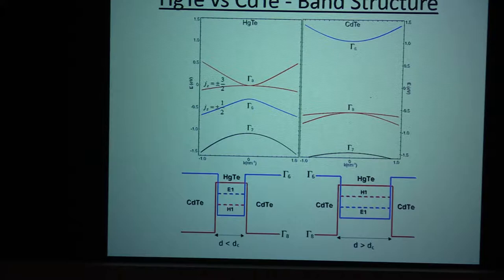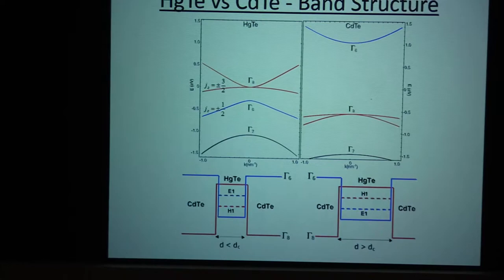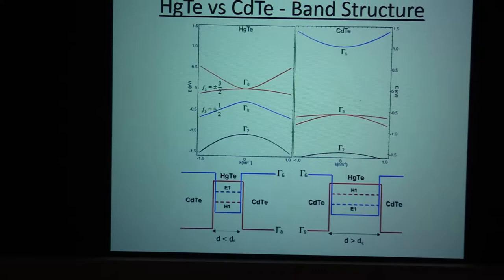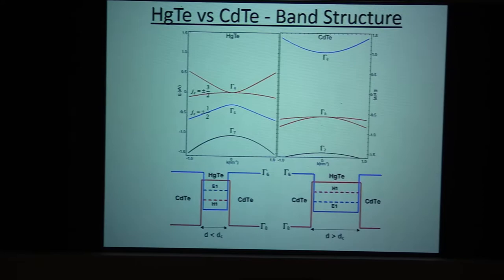So, if we want to actually make this into an insulator, the way to do it is to introduce some energy gap due to confinement. So, imagine we construct a quantum well, which is very, very narrow. So, now we sandwich, we grow a material that consists of mercury telluride, sandwiched between two barrier material cadmium telluride. In the cadmium telluride, you see that, indeed, the blue or the s-orbital sit above. This is the bottom of the conduction band, top of the valence band. And if the well is very narrow, then the fact that these bands were inverted will not matter so much, because as we compress things very tightly in space,